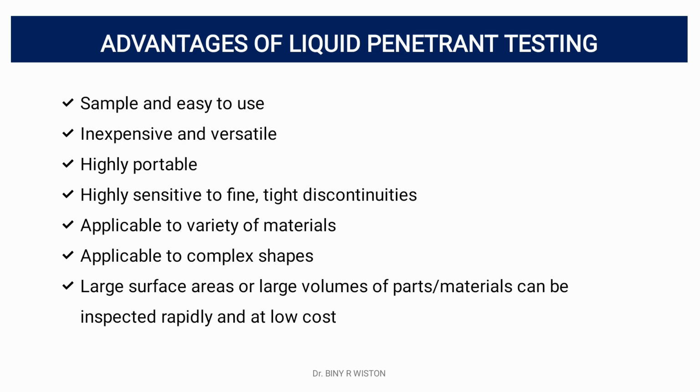The high sensitivity of LPT. LPT can detect very small surface defects, often as small as 0.001 inches, which is 0.025 millimeters, making it highly sensitive. It has versatile application. It is applicable to a wide range of materials including metals, plastics, ceramics, effective for various shapes and sizes of components, and the results are immediate. LPT provides quick results allowing for prompt decision making regarding the integrity of components.